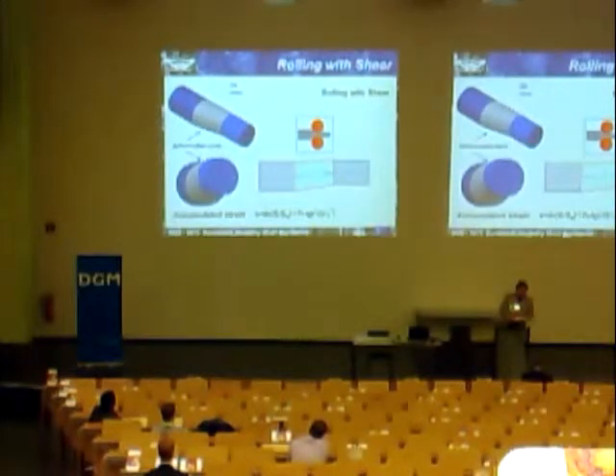Rolling with shear is characterized by variable shear deformation in the process of metal formation within the roller passes. Plastic deformation of metals is accomplished at least twice with partial reduction not less than 10%. A characteristic of the scheme is that rolling in adjacent passes occurs with grooves displaced along the axis of rolls at a distance of 20% of groove width. So there is a 3D model.